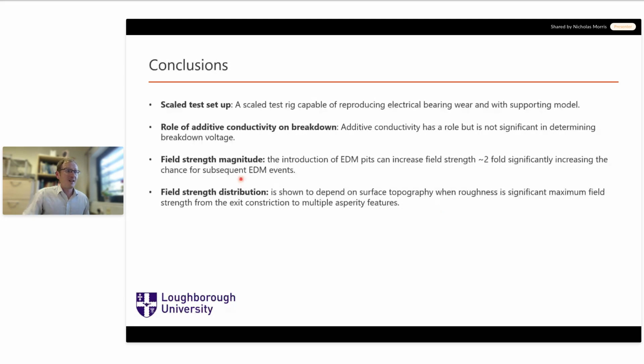We look at the magnitude of the electrical field strength as a result of legacy EDM pits passing through the contact. And we've shown perhaps something of the order of twofold magnitude in electrical field strength can occur. We look at how the surface roughness has an effect in terms of increasing the electrical field strength within the contact if the surface is significantly rough, like that might occur from a fluted surface, but also that the maximum field strength where the dielectric breakdown is likely to occur moves.